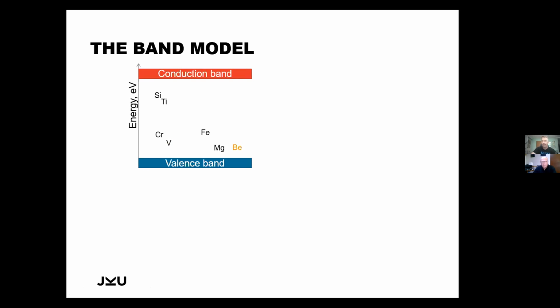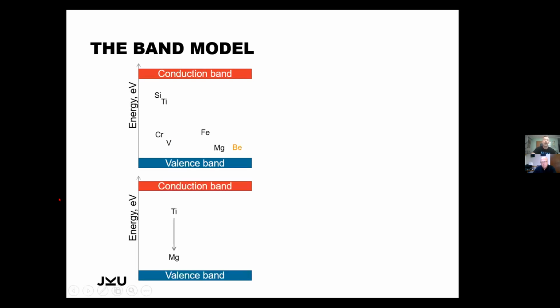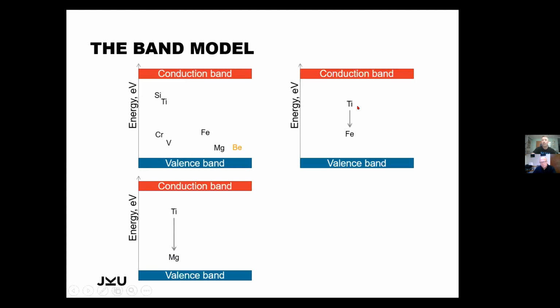However, we have to know the exact chemistry in order to predict the color that we will see, because titanium is a very high level here, and magnesium is a very low level. And if we don't have silicon, for example, which would be even above the titanium, we will always have titanium, which pairs with the magnesium into a charge transfer. However, this energy is larger than the band gap that we have in the visible light, so we do not see color. What we see is the titanium to iron transition.